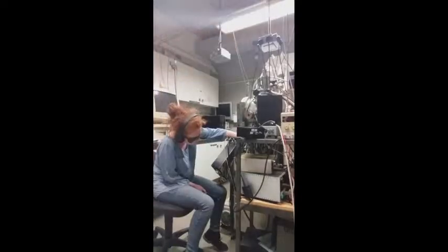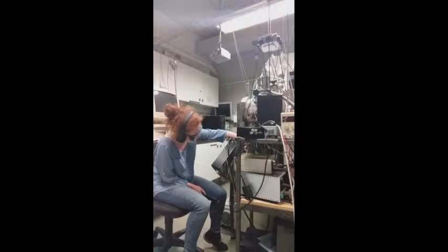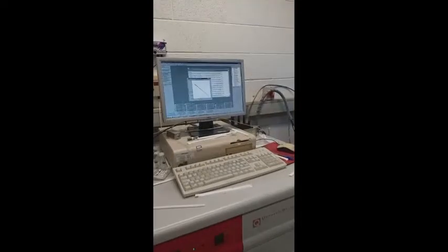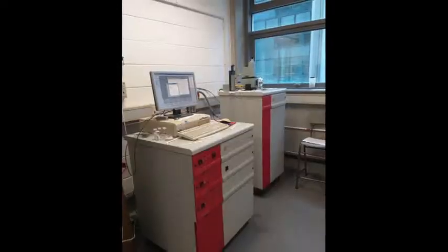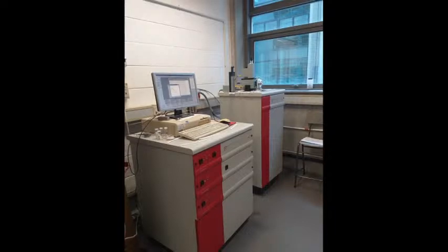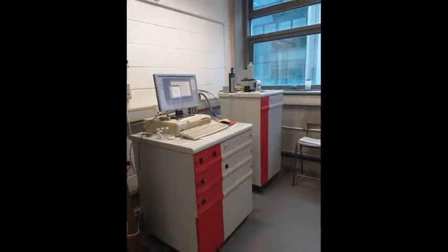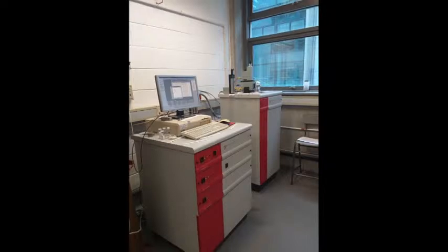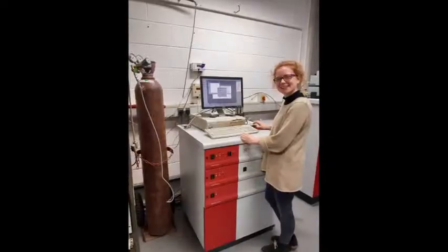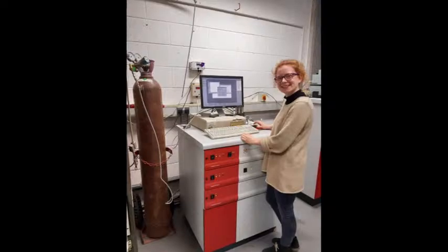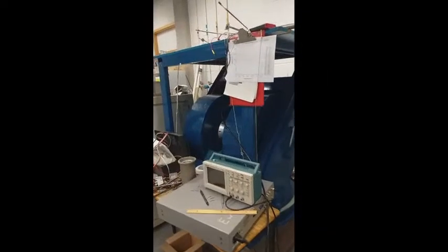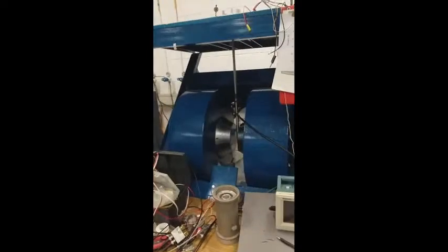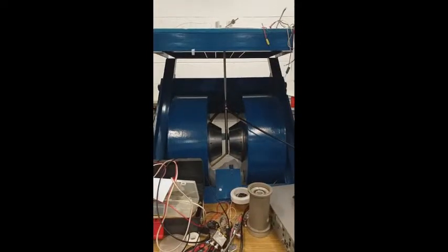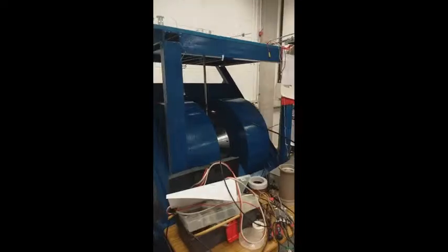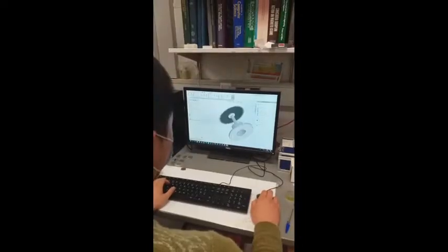After preparing our samples, we need to magnetically characterize them, and the SNIAM is the home of our very own SQUID magnetometer. So SQUID is a strange name, but it stands for Superconducting Quantum Interference Device, and it allows us to apply a magnetic field to a sample and measure the resulting magnetic moment. We can scan fields of up to 5 Tesla. We can also vary the temperature from 4 Kelvin up to about 400 Kelvin. But if we want to measure the magnetization at higher temperatures, we need to use our VSM, or vibrating sample magnetometer, which is being fixed up at the minute. So Zetian, another PhD student in our group, is working on this.